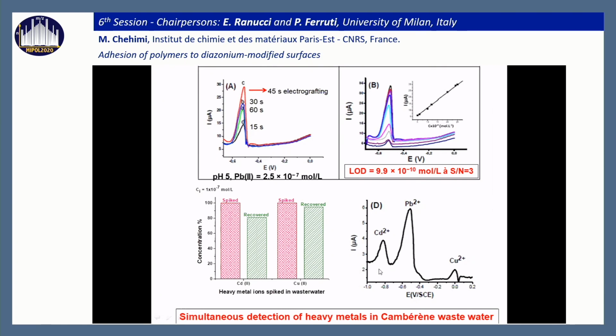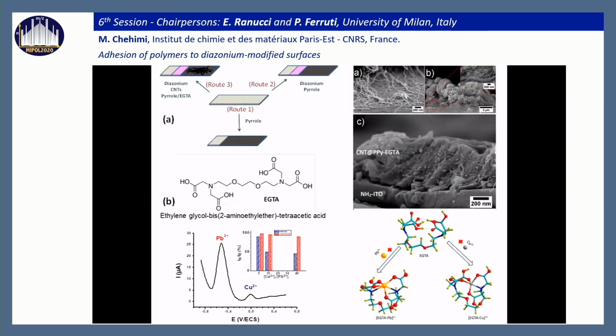We studied the selective recognition of lead with cadmium and copper. But when we mix all the metal ions together in the same wastewater medium, we can have some competition. We improved the selectivity and recovery of lead using polypyrrole and this derivative of EGTA as a chelatant for the metal ion. And you see here, even though we go to 40 times the ratio of copper 2 to lead 2, the recovery is very good for lead with this skeleton used in combination with polypyrrole.